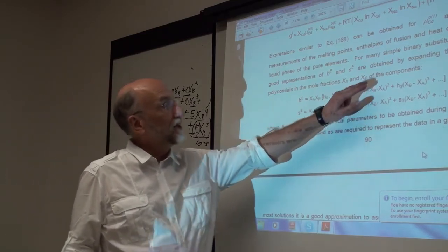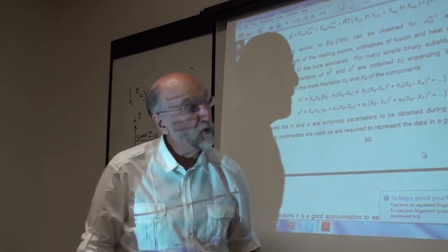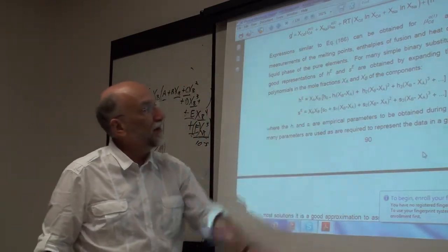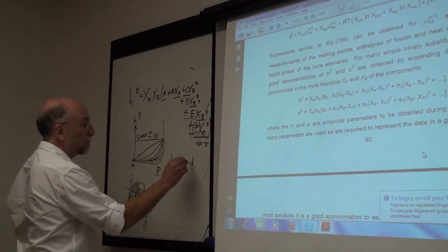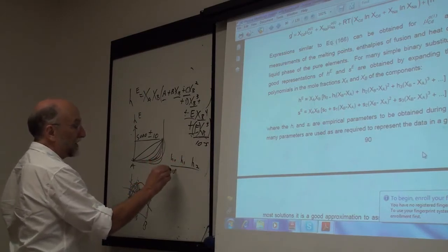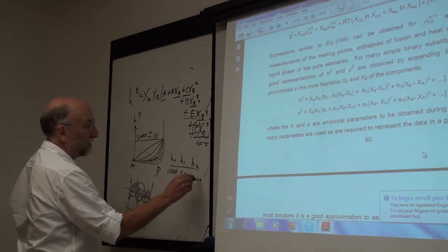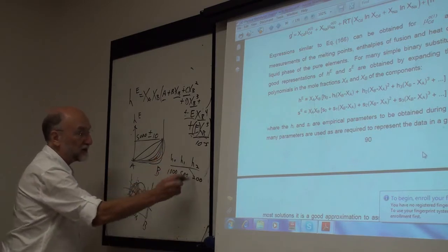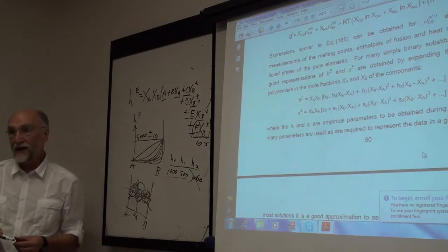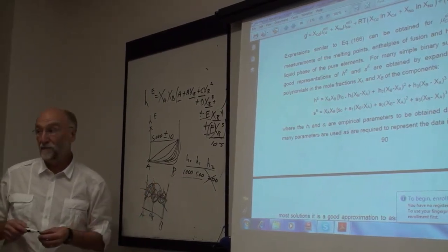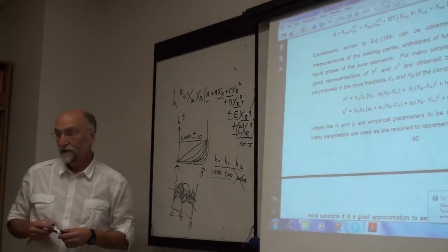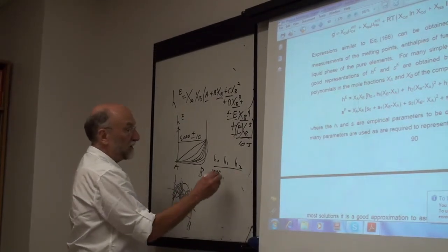The coefficients tend to get smaller as you add more and more terms. They do not remain entirely constant. Say I fit it to 3 terms, I have H0, H1, and H2, and I get 1,000, 500, 200. I say, well, I didn't need the third one, let's just truncate it. You can't quite do that. You then really do have to refit it to 2 terms, but the 2 terms aren't going to vary much from what they were. Let's say you use 1 term, you get 1,000.